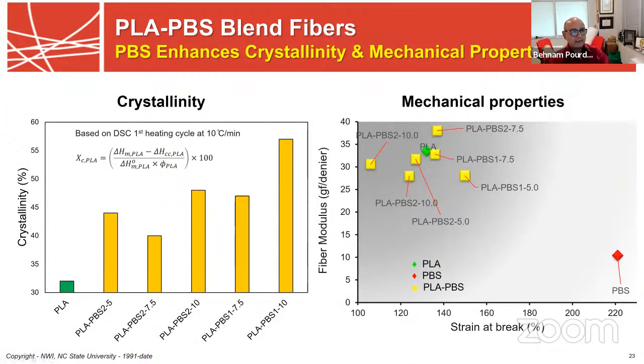When you add PBS to PLLA, it actually enhances its crystallinity. It shows you basically as a function of percentage. So once you get to 10%, you've improved the crystallinity very significantly. You've gone from something like 32% to over 55%.